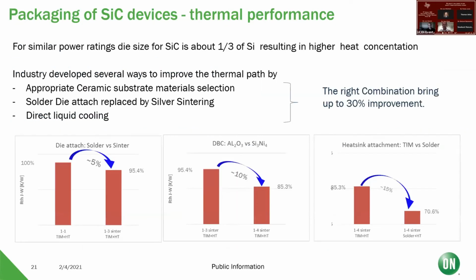The next slide, you see some of the new materials required to accommodate the new power capability. Again, specific to silicon carbide, but you have a 3 times increase in potential heat concentration. The solder needs to be replaced by silver sintering. The interface layers on substrates need to move from aluminum oxide to silicon nitride. Heat sink attachments need to be changing, and all of them allow a significant improvement, or maybe said in a more conservative way, otherwise prevent some of the advantages from showing up at the package level or at the module level, as we will talk about in a minute.